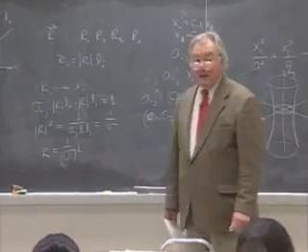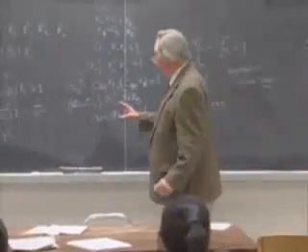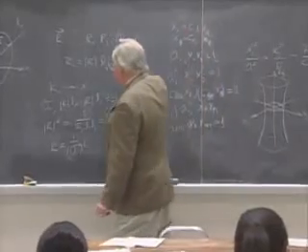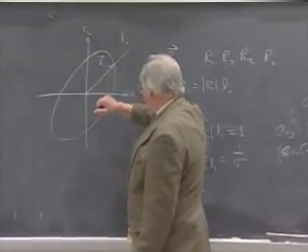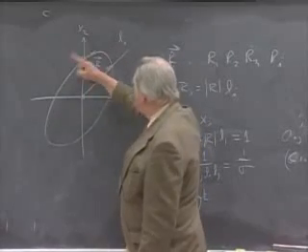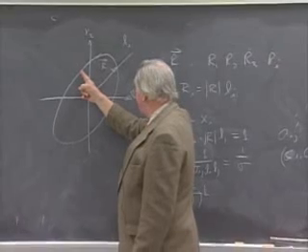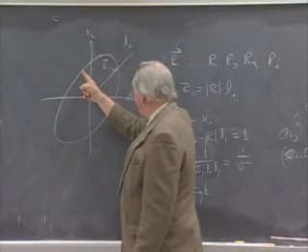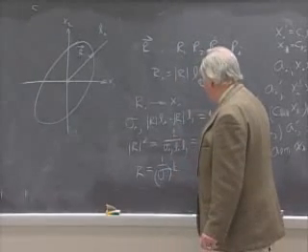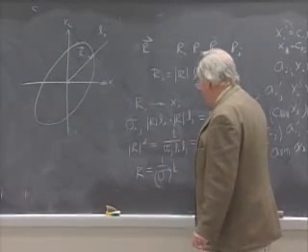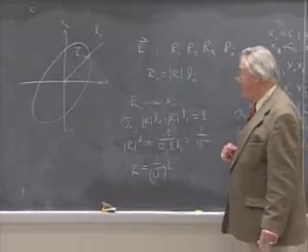So this is why it's called the representation quadric. If you construct the surface from the tensor elements, you will have defined a quadratic form which has the property that as you go in different directions, the distance out to the surface squared is going to be equal to 1 over the property in that direction, or alternatively, the radius is going to be 1 over the square root of the value of the property.